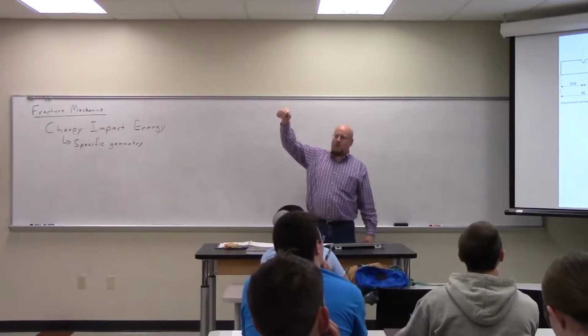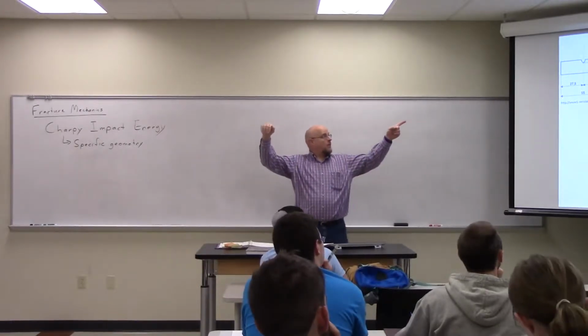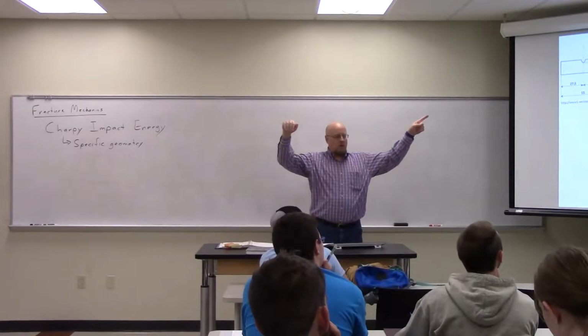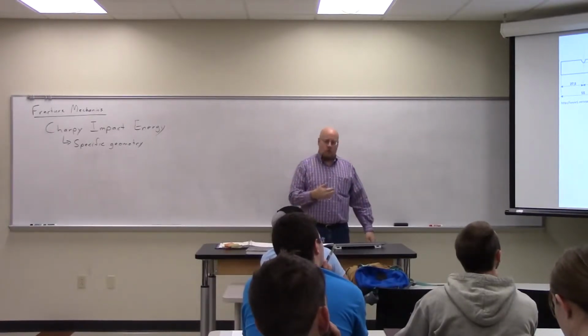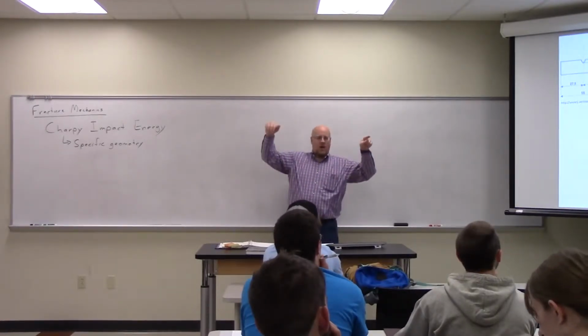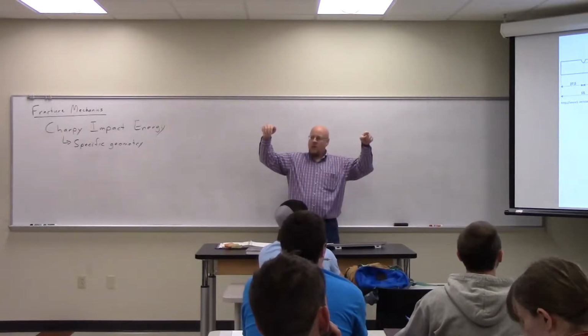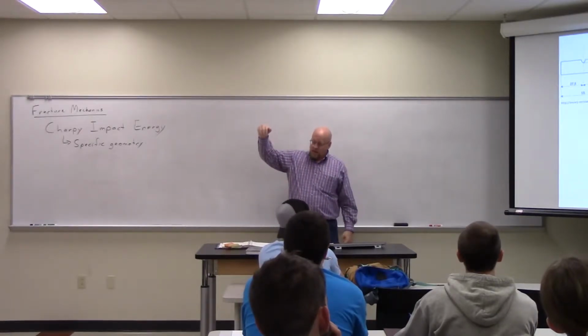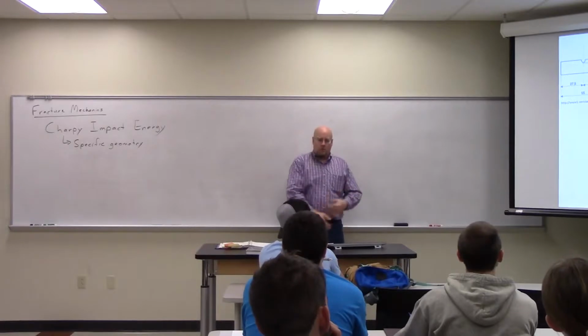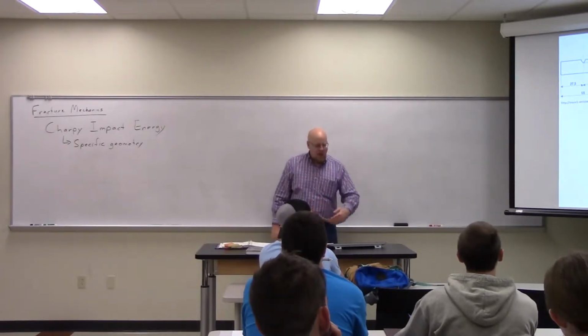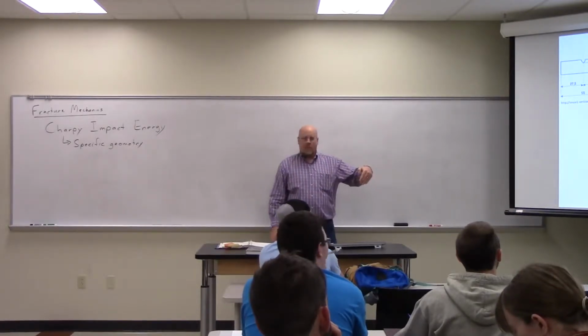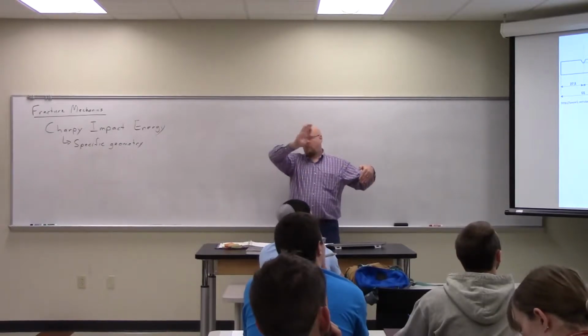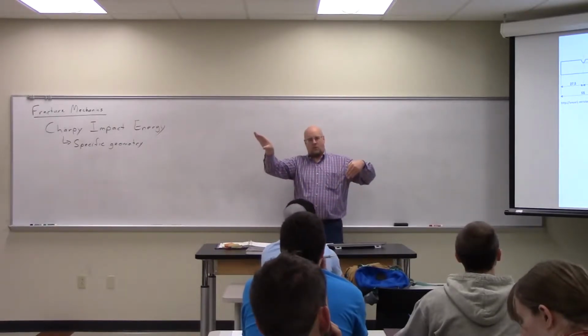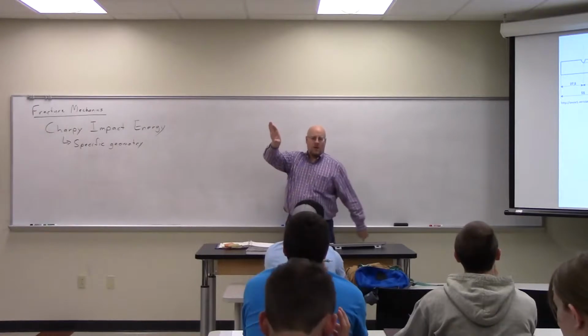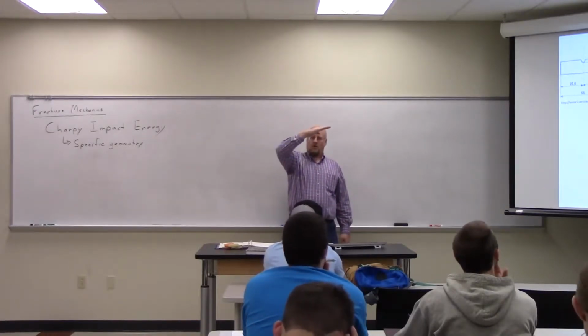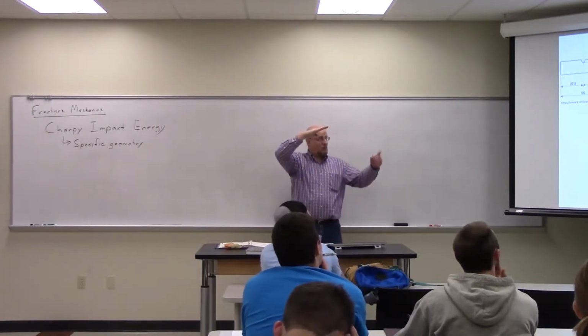So the hammer will be dropped from a known height, so you can see on the top part there's a scale with the pointer. You raise the pointer up and it's telling you what the height of the hammer is. And then you let it go from that height and it comes down and whack! It breaks the Charpy impact specimen and then goes up on the other side. And then there's typically some kind of a little push indicator that maps its travel up, and then it comes back down. And so you can measure, knowing here's the energy it had to begin with, right? The potential energy of the hammer.